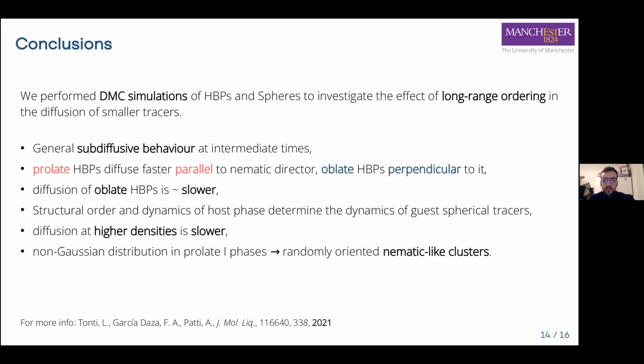Generally, the density of the system affects the total diffusion of the particles, and the denser the system, the slower the diffusivity. And as I said before, we observed this unexpected non-Gaussian distribution of particle displacement for prolate hard board-like particles in isotropic phases, and we think that this is linked to the formation of randomly oriented nematic-like clusters in isotropic phases.